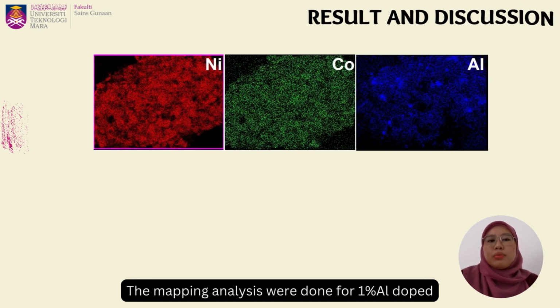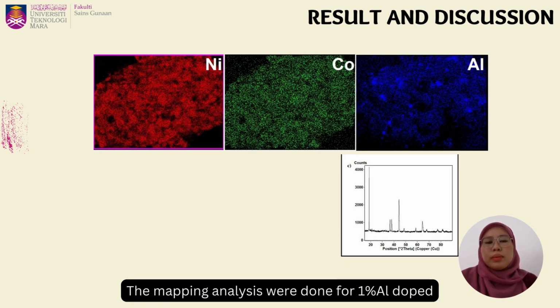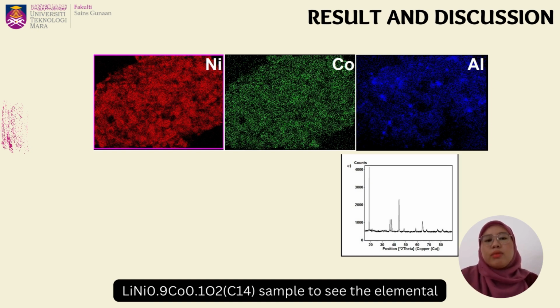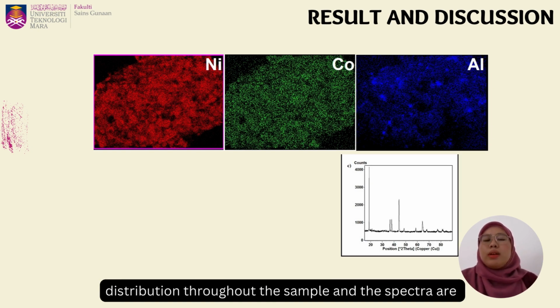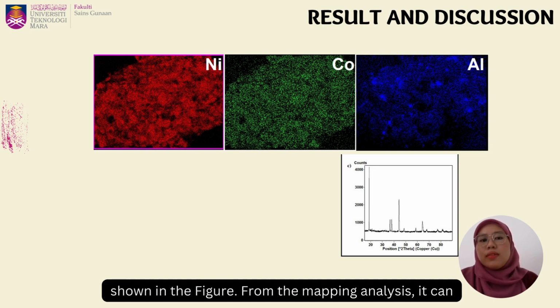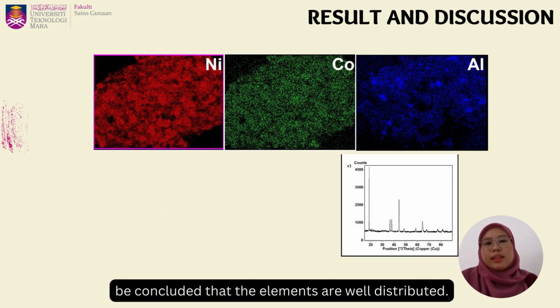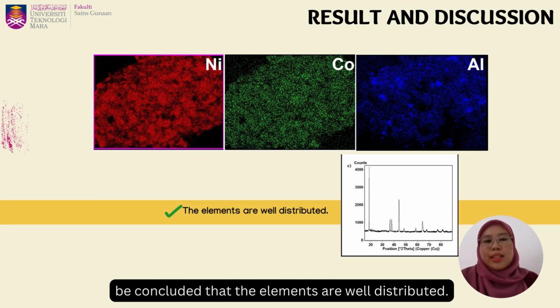The mapping analysis was done for the 1% aluminium-doped lithium nickel cobalt oxide C14 sample to see the elemental distribution throughout the sample, and the spectra are shown in the figure. From the mapping analysis, it can be concluded that the elements are well distributed.